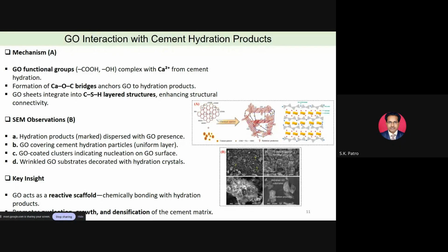So in A, the hydration products are dispersed with the GO present. In picture B, GO covers the cement hydration particles as a uniform layer. In picture C, GO-coated clusters indicate nucleation on the GO surface. In picture D, these graphene oxide substrates are decorated with the hydration crystals. So that is the procedural phenomenon of what is happening in this nano GO. GO acts as a reactive scaffold, chemically bonding between hydration products. That helps the densification of the cement matrix and its growth also.